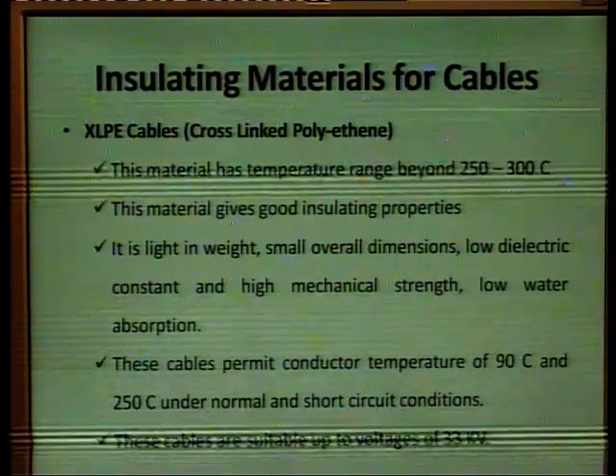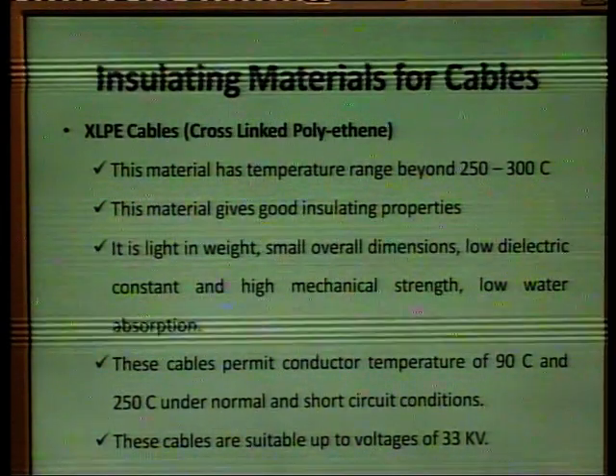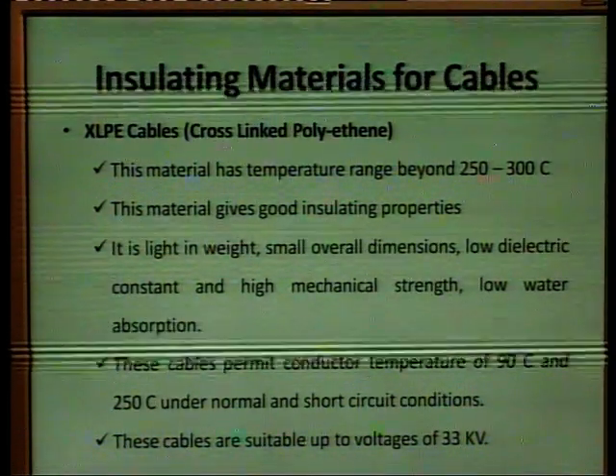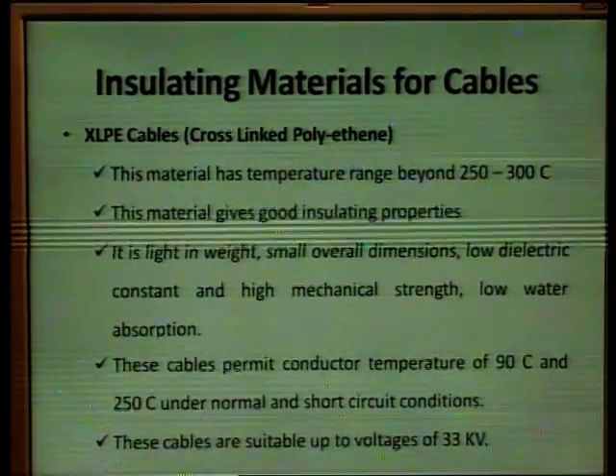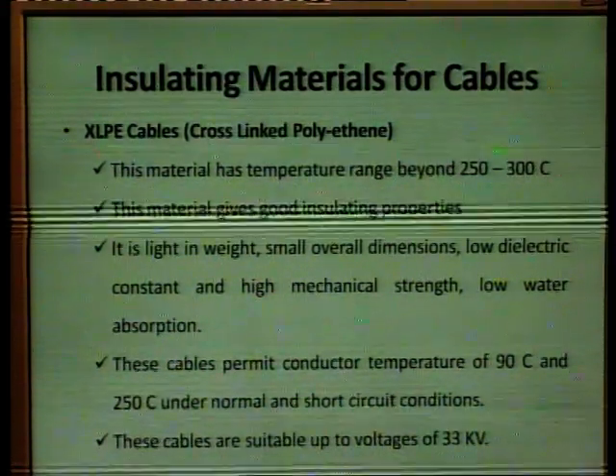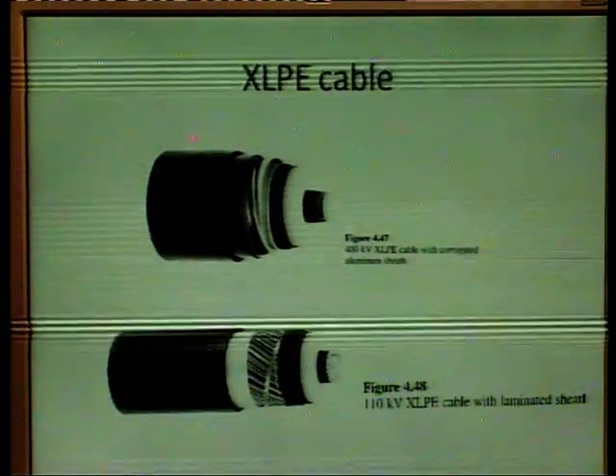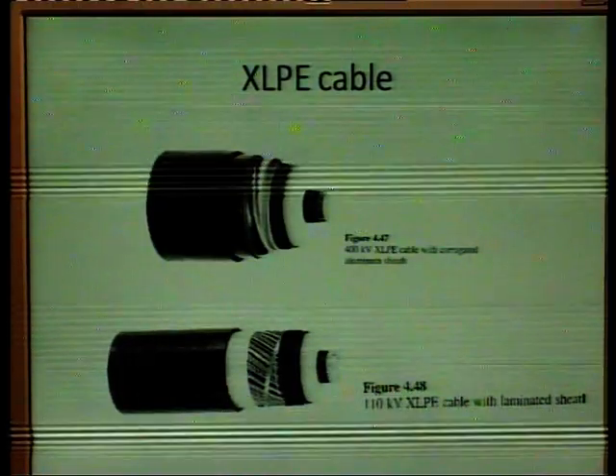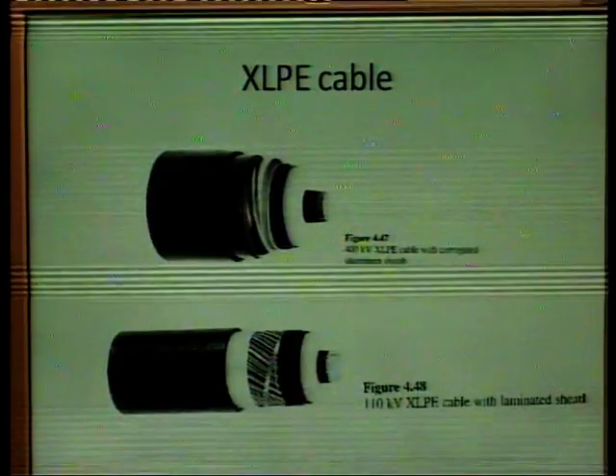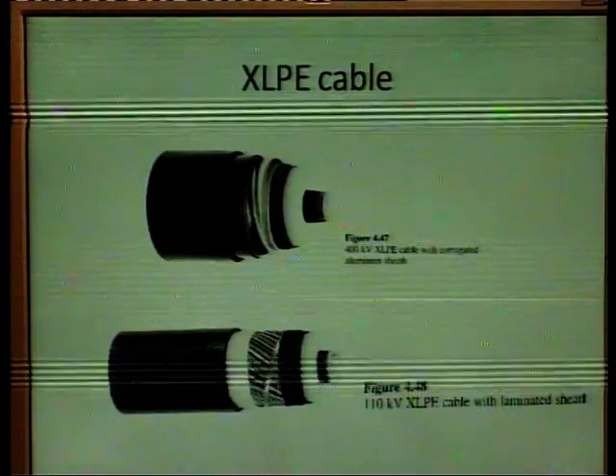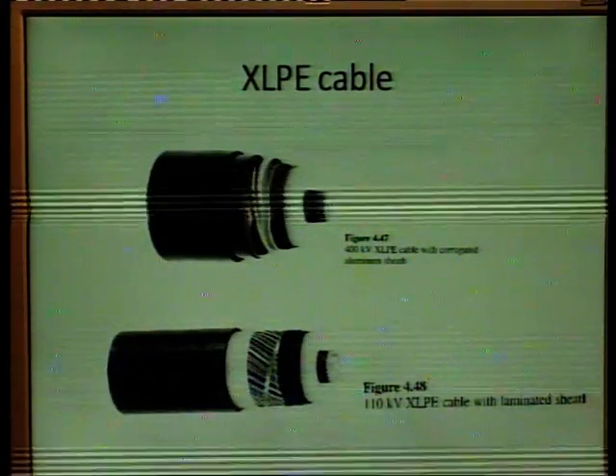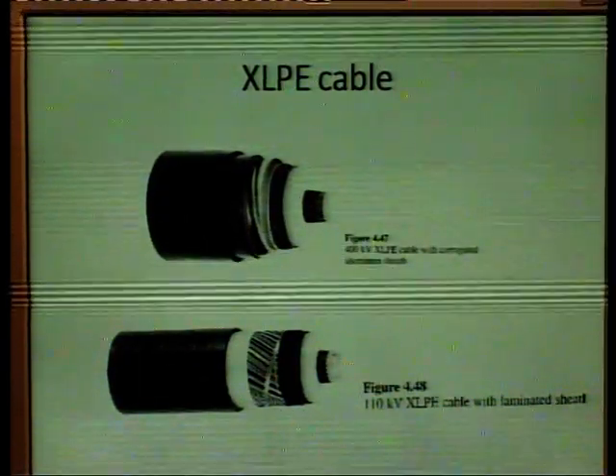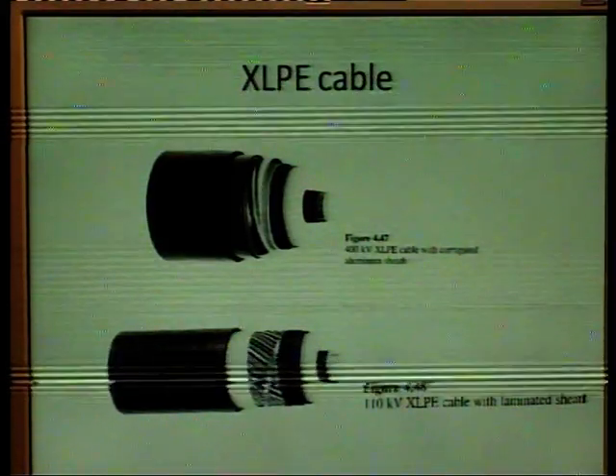And these cables permit a conductor temperature of 90 degrees centigrade under normal conditions and 250 degrees centigrade under short circuit conditions. And these cables are suitable up to voltages of 33 kV. So this is an example of cross-linked polyethylene cables. In the upper figure we can see a 400 kV XLPE cable with corrugated aluminium sheath, and in the lower figure we have a 110 kV XLPE cable with laminated sheath.